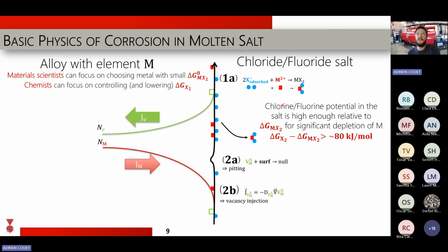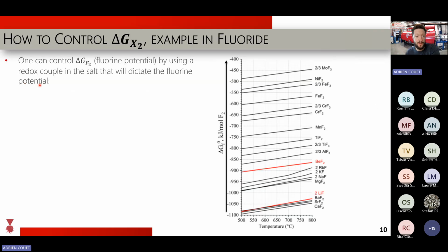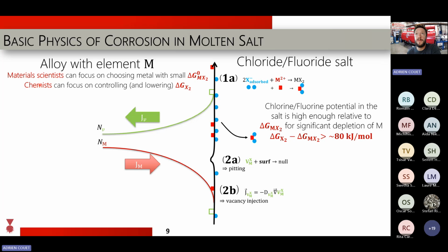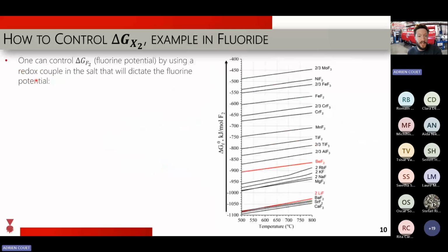So I like to say that material scientists tend to focus a lot on the metal chloride or metal fluoride formation energy, because it's the metal, right? The chemists focus a lot on the partial pressure and activities of species in the salt. But if you want to work on molten salt corrosion, and in many fields of corrosion actually, you need to understand both the material science and the chemistry. That's usually the field of electrochemistry, because that's the field of the interface between materials and environment, and it's one that is a little challenging to fully grasp. Just as a side note, why it's a complex field to work on is because material scientists and chemists followed different paths for many years. They have developed completely different standards and so on, and sometimes it's tricky to get back from one to the other, right?